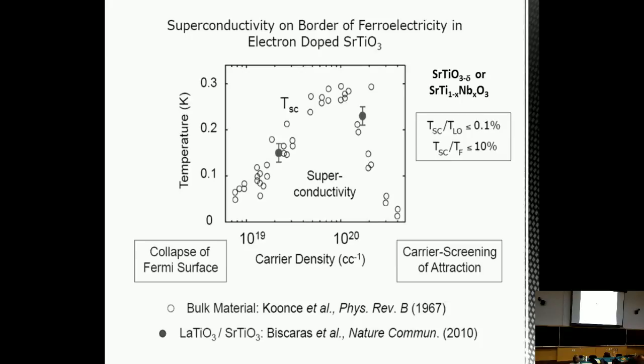So it's clear to understand that Tc should drop down here as the Fermi surface collapses. And then at the high end, the question is, why does the superconducting transition temperature fall at higher carrier densities? And we'll see that that could be related to the screening of the interaction by the conduction electrons. These two red points are the superconducting transitions measured in the layer material, LaTiO3/SrTiO3.